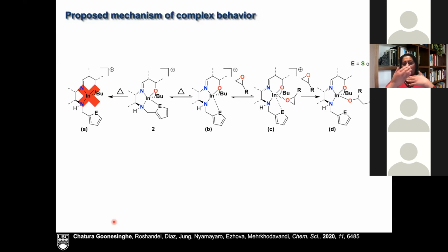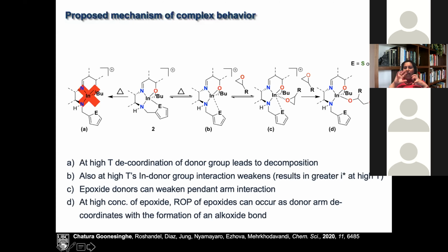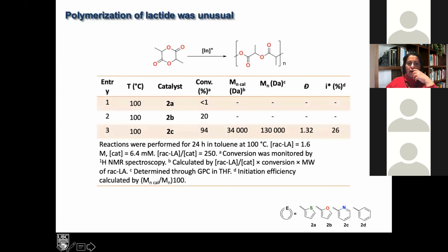So a way to think about this is to think about the mechanism potentially. If we have a system where the donor comes off, we know that when the donors are not really good at binding, the complexes decompose. But if we have a system that coordinates but can dissociate somewhat during our reaction, we have enough coordination space available around indium to coordinate our monomers, in this case epoxides, that would lead to cationic polymerization of these systems. And so this idea of having those hemilabile arms, and specifically the oxygen donors seem to be in the sweet spot for these systems, allowed us to tune the reactivity of these catalyst systems.